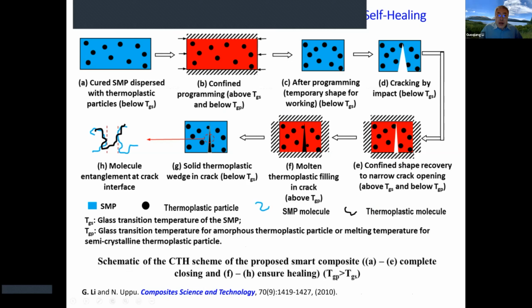Okay, and then you heat it up, or even not heat it up, you can do a compression programming. You can see you add compression first. So after you deform to the level you desired, you cool down, you remove the load, and you can see the volume of the synthetic foam has been reduced from here to here. So this shape can be put in service.